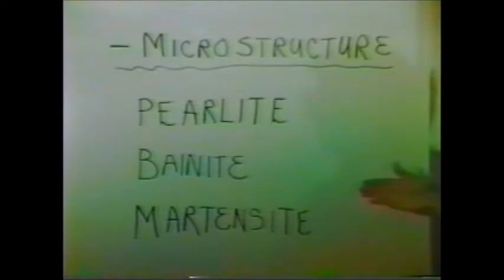and martensite. Now, pearlite is generally the most desired microstructure for machinability. And it really deals with the steel cooling through 1330 at the slowest rate of the 3 for the different structures. If we jump for a second to martensite, the cooling rate for martensite is so fast that the carbon in the steel at high temperature does not have a chance to diffuse into the low temperature steel. In other words, the carbon gets kind of locked in as to where it was when it was at the high temperature form. So when you lock in the carbon, you create a very hard structure called martensite. Again, this structure is very desirable in terms of alloy steels when you want to heat treat for high strength, but it is absolutely no good for machinability.